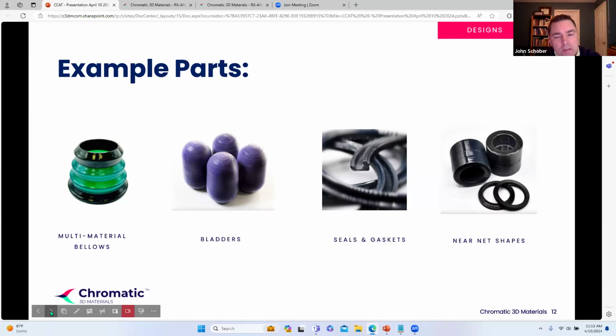Yeah, so the images that you see here are reflective of the range of the geometries that we can print. You see here on the left bellows, which shows the multi-material printing, and you see the green and the black, and those are different materials. The way we printed this one, it was more rigid towards the edges and softer towards the middle. The green is the softer material. We actually printed that without any supports. So we do have the ability to print overhangs. That's not an unlimited ability, as with any other 3D printing technology, but with different constructions we are able to print without supports.